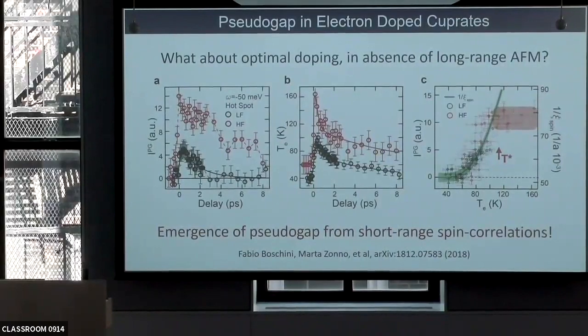The green line underneath is 1 over the spin correlation length. So basically, you have a low temperature state, which is not a long-range order antiferromagnet, has a finite correlation length, and as you go up in temperature, it gets shorter and shorter, and so what you see is a diverging 1 over xi over here. And there is an interesting point, which is the one that defines T star, the onset of the pseudo gap, and that's basically when you see that the intensity of the hotspot departs from the curve, and that's basically when the broadening is of the order of the pseudo gap itself.